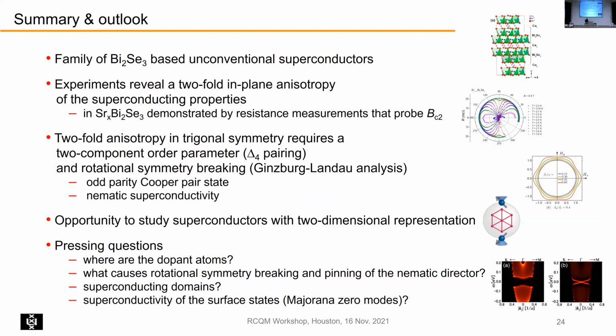So here's my summary. You can read it yourself. I want to stress, as regards pressing questions, where are the doped atoms? That's still an issue. Why is there this pinning of the nematic director? Probably strain. Can we have superconducting domains? And I did not address this, but there is also some theory which tells you where you could find the Majorana zero modes, which are here, for instance, in the gap. I have a slide about that if you want to ask me.